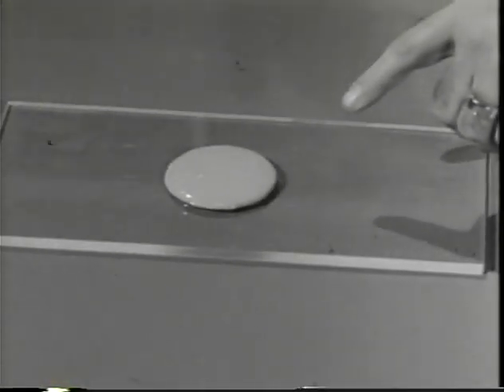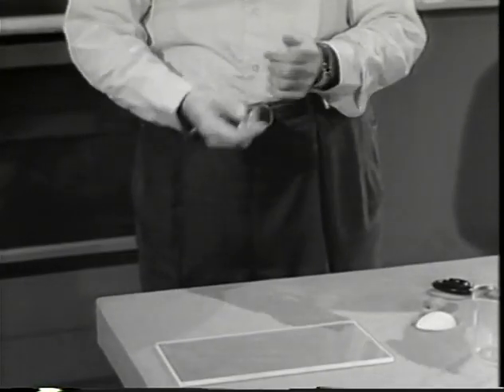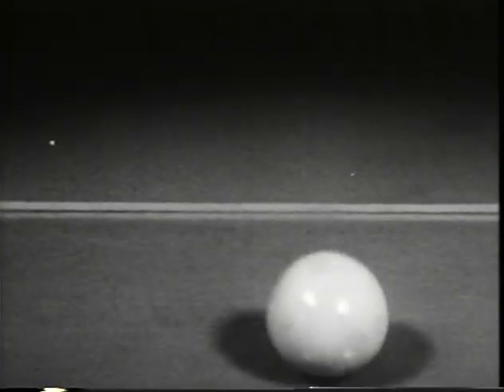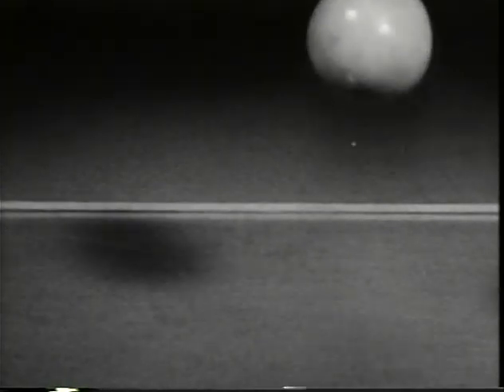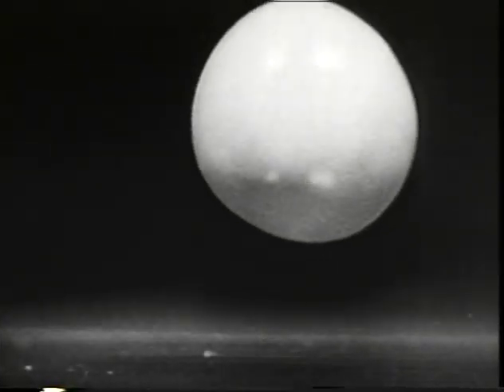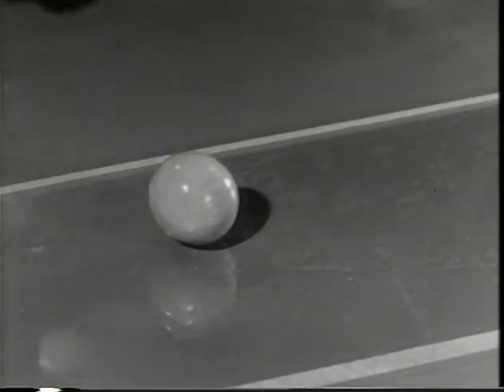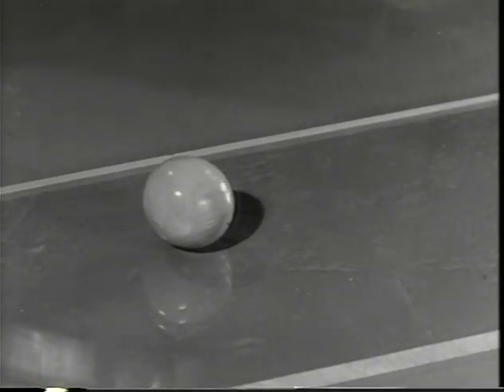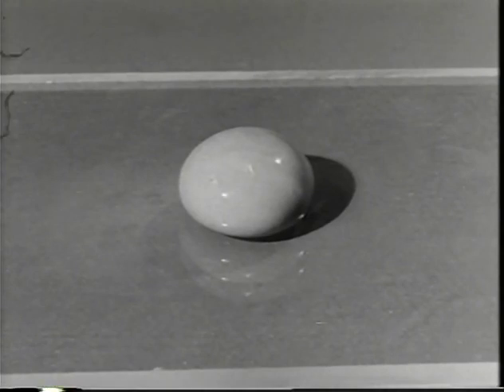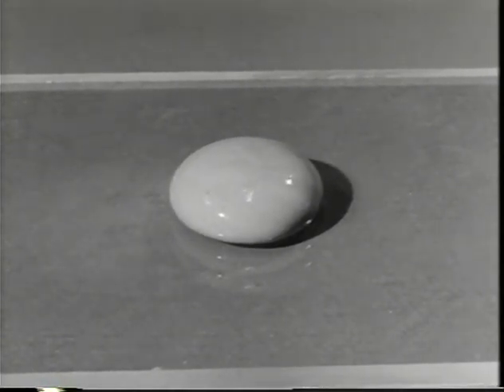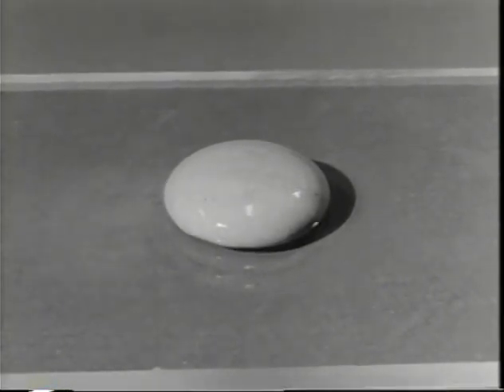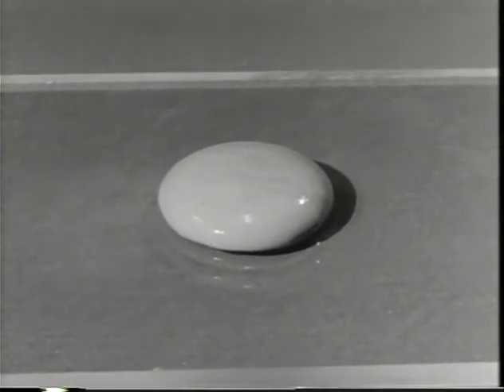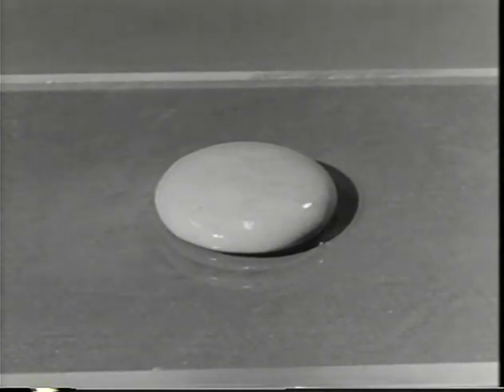Remember the fluid ball? It was like an elastic solid during the short impact of bouncing. An elastic solid has a preferred configuration to which it will return when stresses are removed. A viscoelastic fluid behaves similarly if the stress has been applied only for a short time. But in contrast to the elastic solid, the fluid's memory is not perfect. This time-lapse sequence shows that if the stress acts for a time long compared with the relaxation times of the fluid, the fluid forgets its previous state. In reality, it took 45 minutes for the force of gravity to change the ball into a puddle.